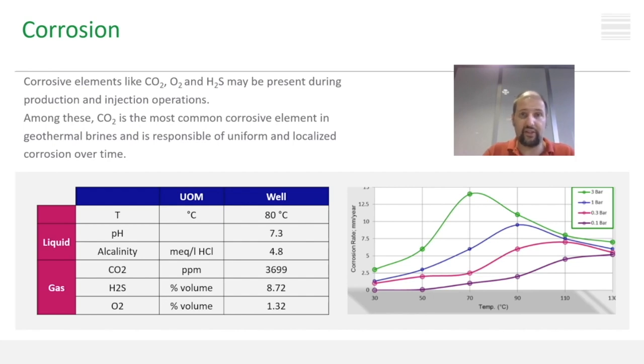In the slide, we can see a particular behavior of CO2 corrosion, which shows a peak at 70 degrees Celsius. Past this value, the corrosion rate counterintuitively declines. This is due to iron carbonate, which, given its reverse solubility, tends to precipitate at temperatures above 70 degrees Celsius. The precipitated layer, covering the surface of the casing, has a protective effect, reducing the corrosion rate.